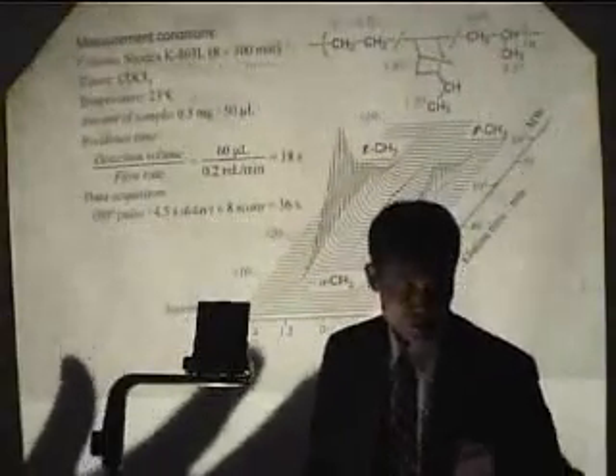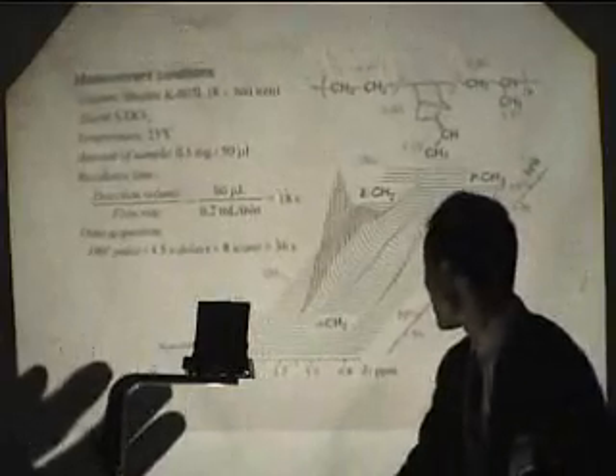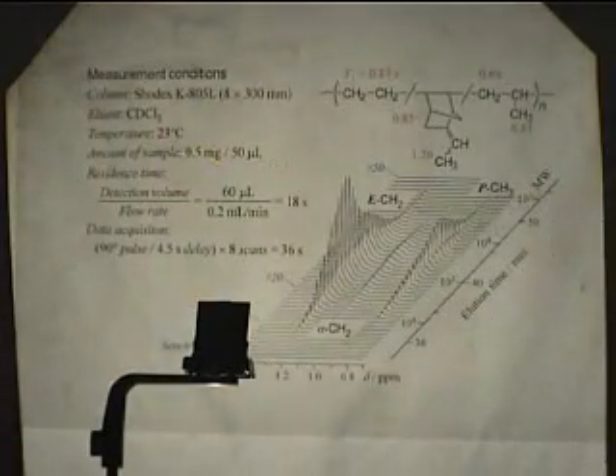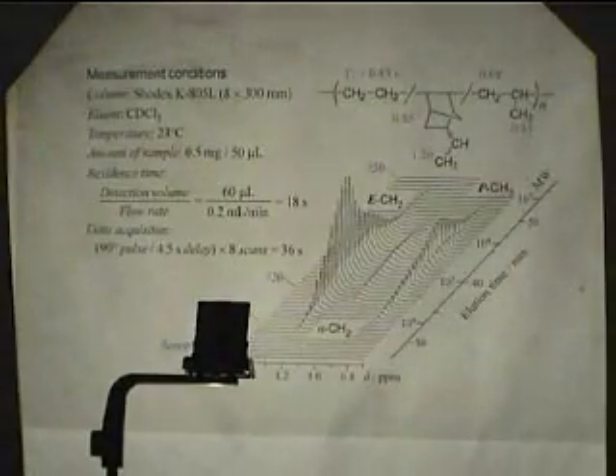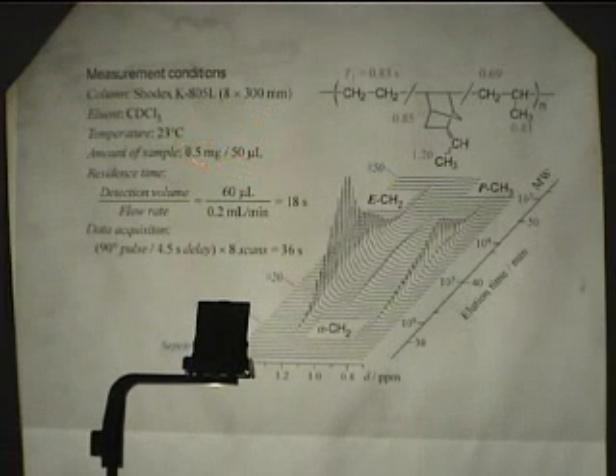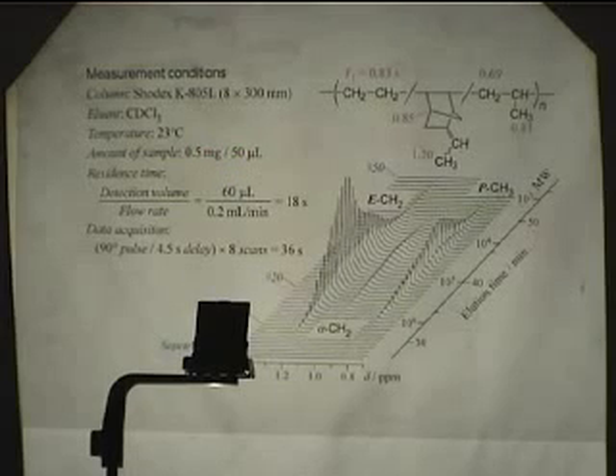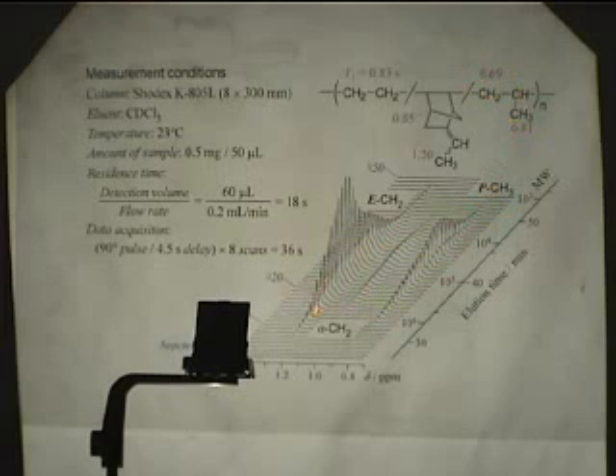The online measurement of this EPDM was carried out using the SEC-NMR method. The amount of sample used for the analysis is 0.5 milligram or less. The flow rate of the liquid is 0.2 milliliter per minute. Eight scans were accumulated for each spectrum, and the total measurement took about 60 minutes. This is the resonance due to the methyl group in the propylene. This is the resonance due to the methylene group in the ethylene.